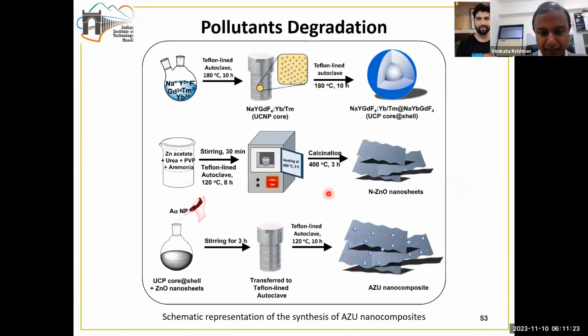So this is how we did it. We prepared the upconversion nanoparticle separately. Then we prepared the N-doped ZnO separately. Then we combined these two together. Then we prepared the gold nanoparticles in appropriate size. Typically, the gold nanoparticles are around 17 nanometers. We used a seed-based technique, an 8 nanometer seed, which is subsequently grown to about 17 nanometers. Then we mixed that in, and the gold nanoparticle concentration is only 2 weight%,